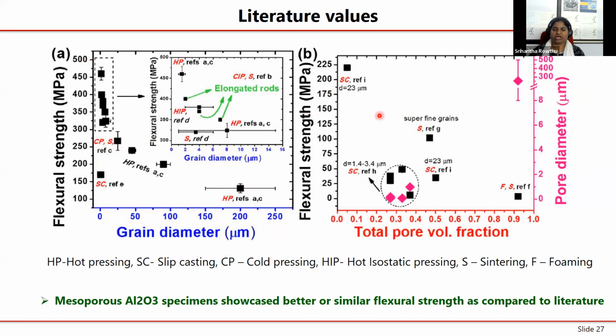When you look at the literature, there is not much available for flexure strength measurements as a function of porosity. There are a few articles, and if you plot that, on the y-axis the flexure strength values are around 225 or so, and as the porosity fraction increases, obviously the flexure strength has dropped. Comparing the data we got with the literature, we can say that alumina samples showcased better or similar flexure strength as compared to literature. So it's okay to continue with these substrates and conduct our tribological testing.